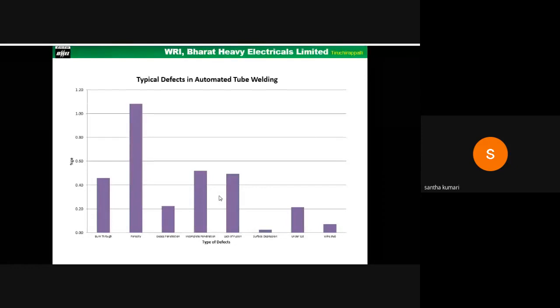This graph shows the evidence of the number of defects which had been calculated, that is per shift, for a longer number of days, per month or per year. If you evaluate the defects in the welding shop, this had been collected cumulatively, and defects like gas hole, burn through, and fusion related defects are the major ones in tubular welding production in our boiler shops.